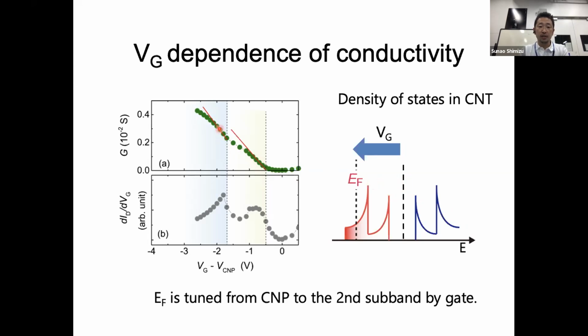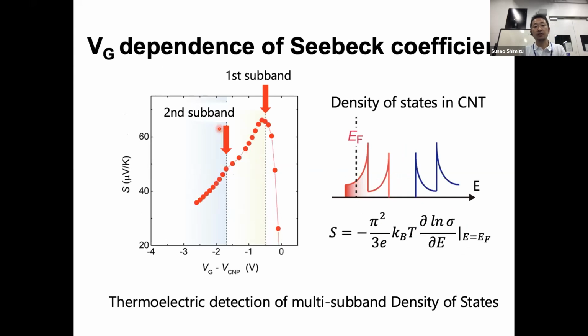We also observed this kind of anomalies in the Seebeck effect. This is the first subband edge, and this is the second subband edge. At the first subband edge, we observed a large value of the Seebeck coefficient, and at the second subband edge, we observed some anomalies or kink structure here. This is because the Seebeck coefficient is also related to the density of states. This equation, which is called the Mott formula, can be found in textbooks of solid state physics. According to this equation, the Seebeck coefficient is related to the energy derivative of conductivity or density of states. So we can clearly see those anomalies in our measurements.